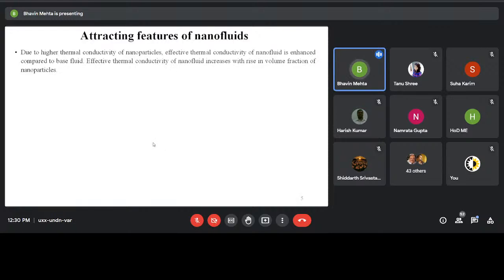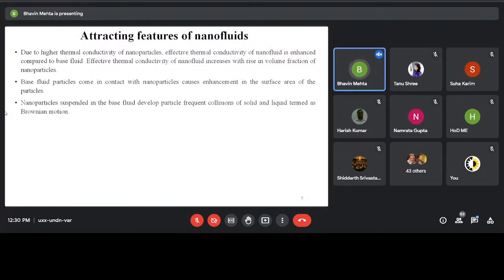I will just quickly go through the attractive features of nanofluids. Basically, due to the higher thermal conductivity of the nanoparticles compared to the base fluid, the effective thermal conductivity of the nanofluid is quite high compared to the base fluid. The base fluid particles come in contact with the nanoparticles and form a hydrodynamic layer, and that causes the enhancement in the surface area. Basically, the nanoparticles suspended in the base fluid develop collisions of the particles, which is called Brownian motion. That also causes the enhancement in thermal conductivity.